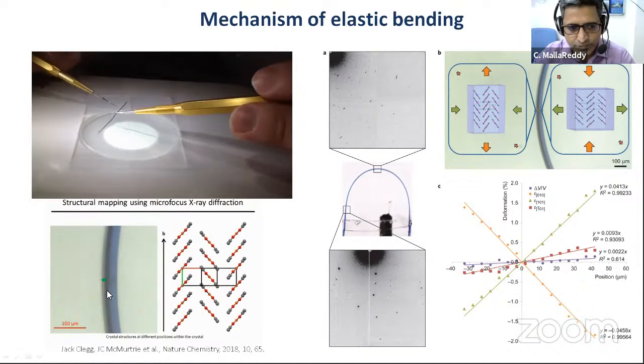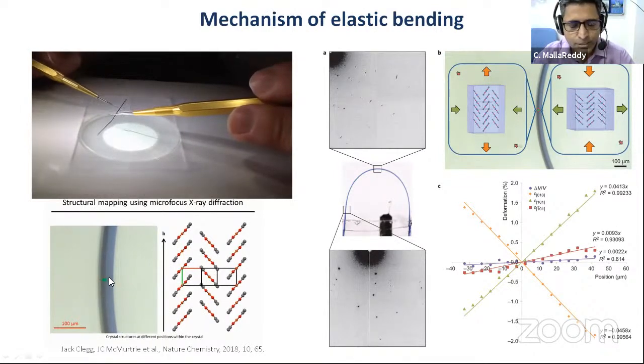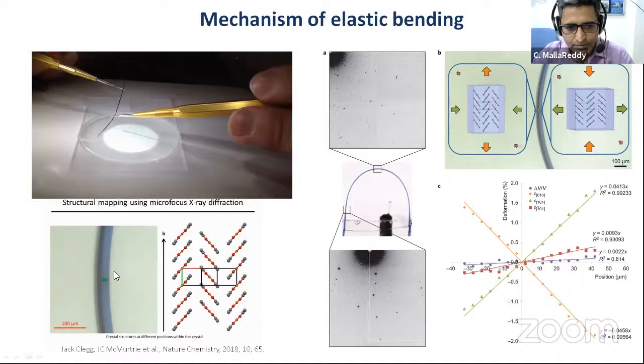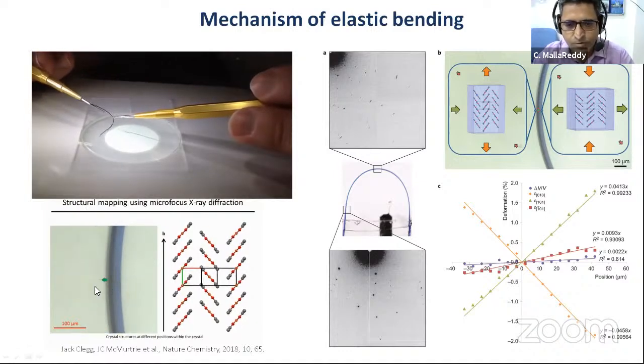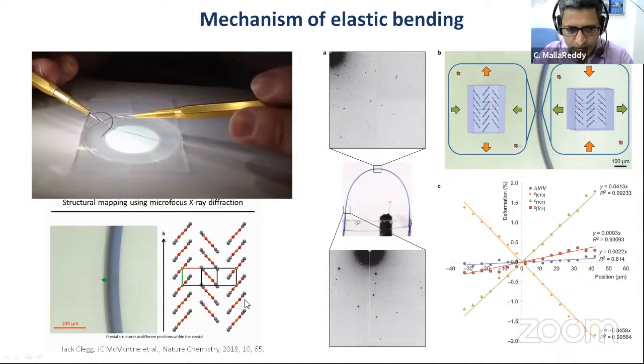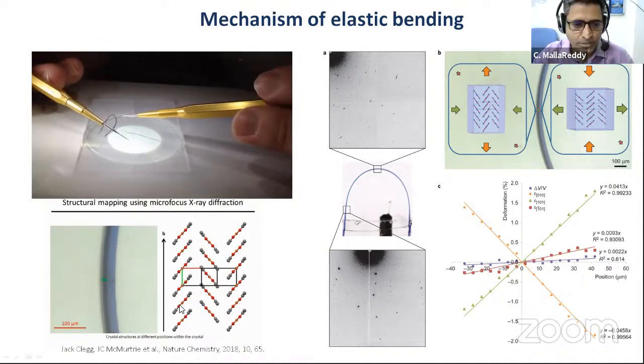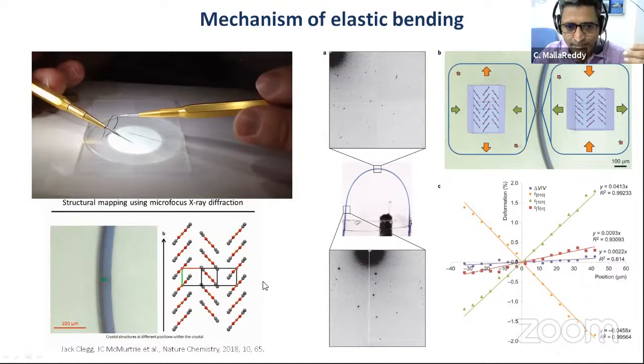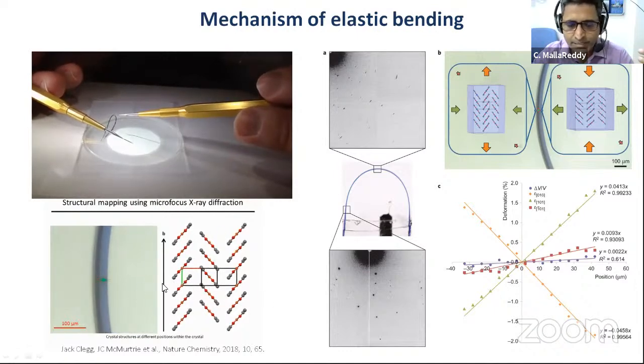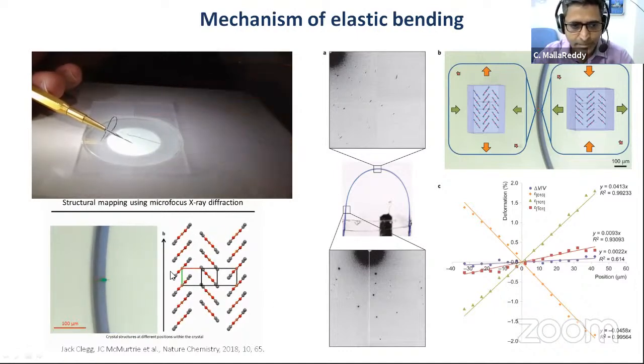Of course, here the bending that they have done is very, very small, and the percentage of strain they could get in this particular crystal is around 1%. But there are other crystals which can go up to 10%. So in those cases, if the mechanism is exactly like this, then you would see much larger changes. But this shall give us some idea about the bending mechanism.